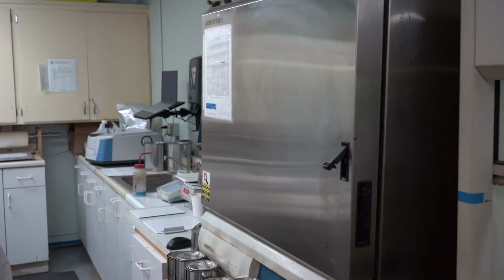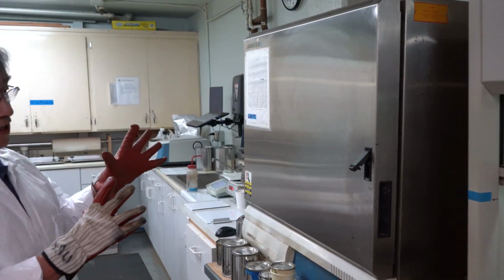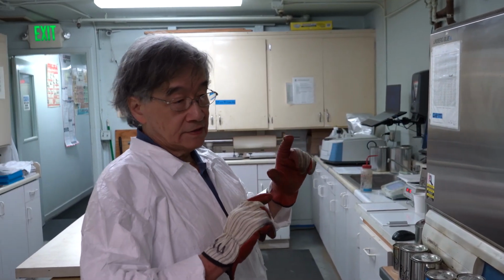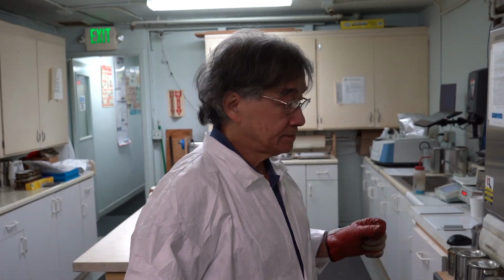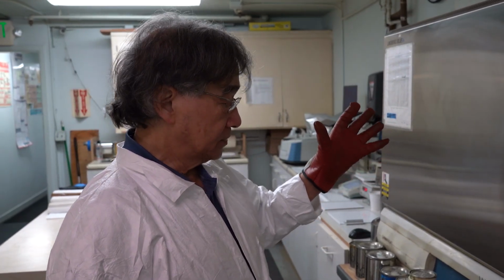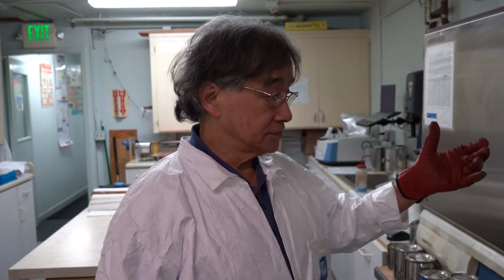At this point, I want to show you around the lab and give a little demo on how to handle the materials from the beginning to the very end, hopefully. So to start, I already have the epoxy asphalt Part B formulation in the oven to get softened, to be used later. And this has been at 125 degrees C for the past 45 minutes.